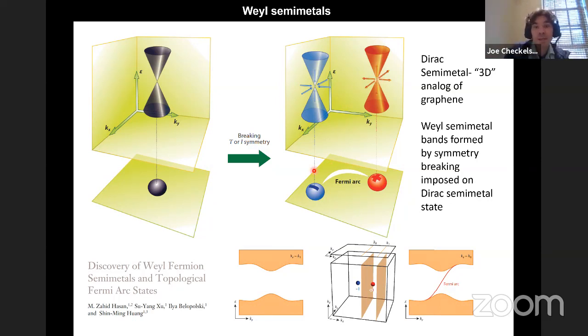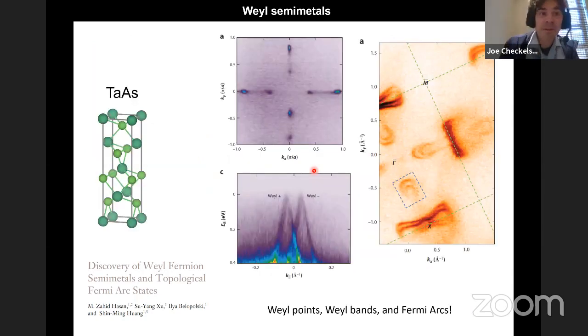And the inversion breaking type of this material, for example, tantalum arsenide, was very soon after these predictions demonstrated in a very beautiful way by photoemission spectroscopy. So the idea is that this is kind of looking at the bulk electronic structure, and it is indeed characterized by these points, right?